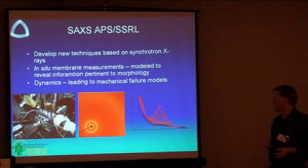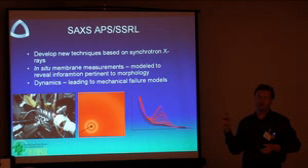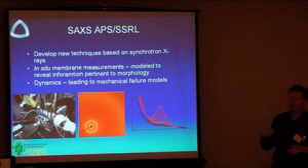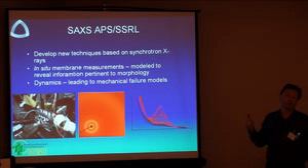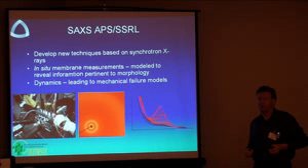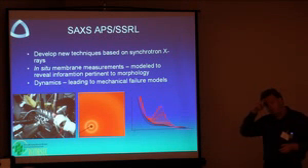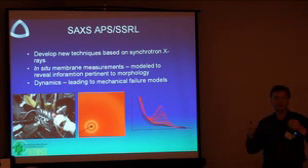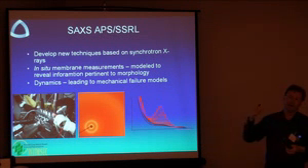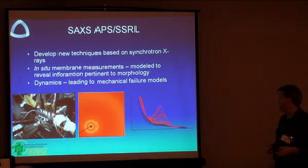Now, this is important for 2 reasons. One is that the memory of the material affects its proton conductivity. So you need to know something about the morphological changes during film forming. And the other one is, even though we know that the PEM falls apart due to hydroxide, it still falls apart because you're going up and down around the glass transition temperature when you run these devices, and the things just form pinholes. So if you can get an idea of the dynamics of nanometer scale morphological changes, you should be able to extrapolate out to a micron scale model and be able to predict when pinholes are going to form.